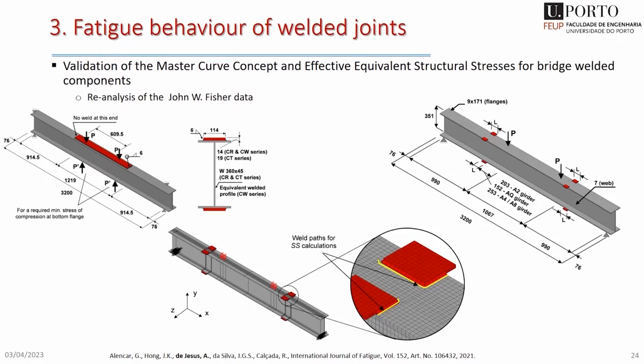And at that time, John Fisher ran in his laboratories very important tests during more than 10 years, maybe 15 to 20 years. So we are talking of large-scale components of welded joints. In that time, this was used for the application of nominal stresses and hotspot stresses. Again, in this case, we revisit this data and apply this new definition with the master curve concept, because we tested that for pressure vessels, not for the typical details on welded bridges.